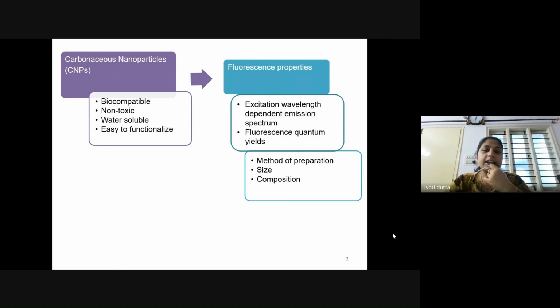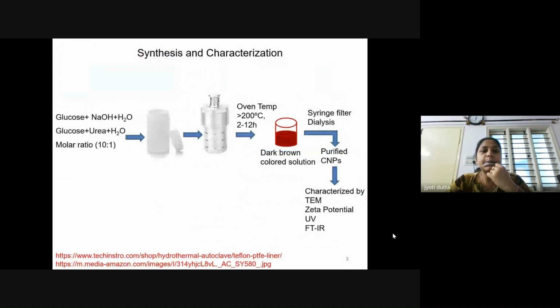Now, we have seen in the previous literature that it is always dependent upon the method of preparation, the size of these nanoparticles, and whatever composition these nanoparticles consist of. Now, I would like to mention that in the present work, we have synthesized two different nanoparticles, and the composition of these two carbonaceous nanoparticles varies because of the different additives that we have used. So we have opted for a hydrothermal synthesis procedure, and these nanoparticles consist of glucose. Glucose is the major ingredient, and in one set of nanoparticles we are not adding any additive, whereas in the other set we are using urea as an additive, and the medium for the synthesis is water. So the molar ratio that we have opted for is 10:1.